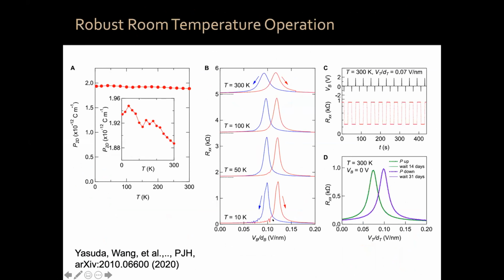So this is essentially the question that you're asking. Another way of looking at it is we can induce a charge density change in the graphene of the order of, by the way, you can see here, the voltage you apply by the back gate divided by the distance. In volts per nanometer, if you wanted that, it's of the order of 0.1 volts per nanometer, okay? That we are applying to induce the switching. So it's actually quite small. The change in density of the graphene that we can induce is of the order of 2 times 10 to the 11, okay? So you can look at either of these three quantities.